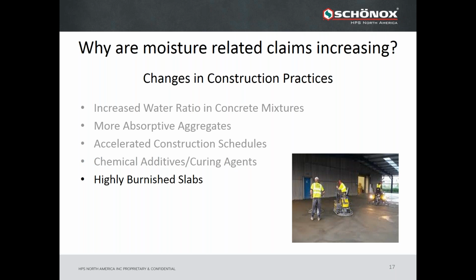And many aren't aware that even the finishing of the slabs, that of the mechanical procedures used in the equipment, can highly burnish the finishing of the slab. It brings the pure Portland cement to the surface, causing it to cure on the surface, closing the slab surface, and this actually slows down the release of the moisture that's trying to escape into the conditioned project space.